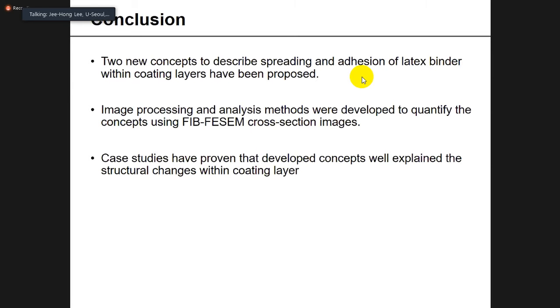we developed two novel concepts to describe the spreading and adhesion behavior of latex binder within the coating layer. And image processing and analysis methods were developed to quantify the concepts using FIB-FESEM cross-section images. And the case studies were applied and have proven that the developed concepts well explain the structural changes within the coating layer.